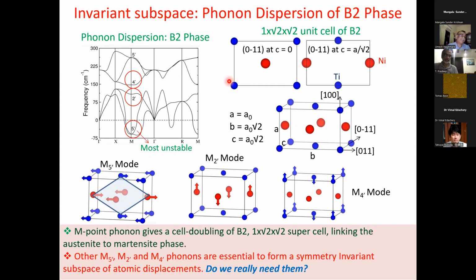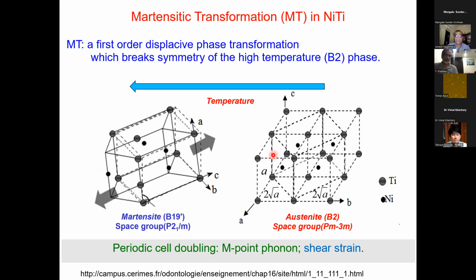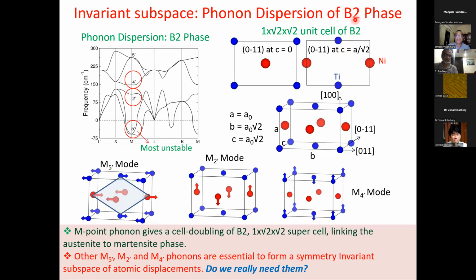So again, just like in barium titanate, we start with phonon dispersion of the B2 phase, which is the high temperature phase. And as you expect, it has unstable modes. But unlike barium titanate, it doesn't have so many unstable modes. Most of the unstable modes of B2 phase are at M point of the Brillouin zone. M point is basically zone boundary point, which means these phonons will lead to cell doubling if you freeze in the double well energy function. So this is the phonon which is unstable, which involves displacements of nickel and titanium against each other.